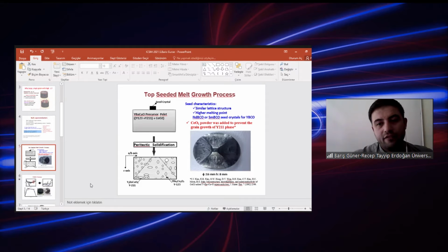And then we have to use cerium oxide powder, because cerium oxide powder was added to prevent the grain growth of the Y211 phase. In our previous works we studied the behavior of the cerium oxide powder. When we add the optimum amount of cerium oxide powder, we can fabricate good single grain YBCO. So the peritectic solidification is like that. During Tmax, the maximum temperature, Y211, Y123 and cerium oxide combine and go to a good single grain microstructure.